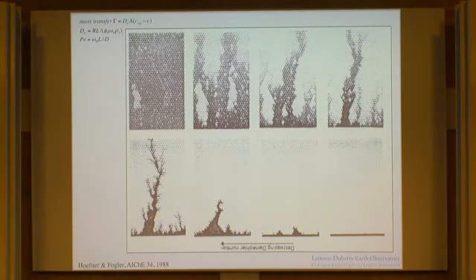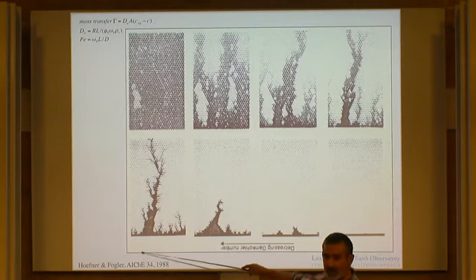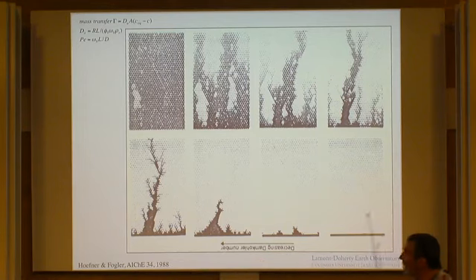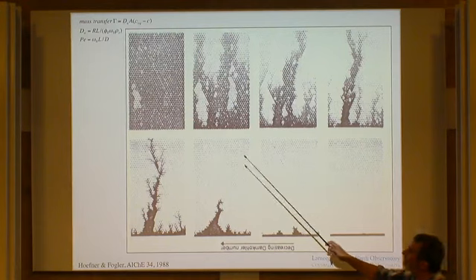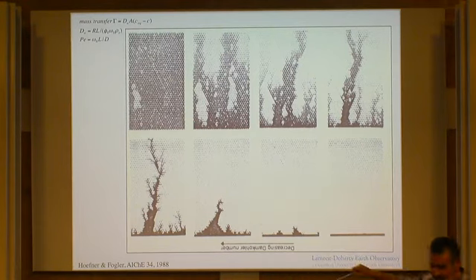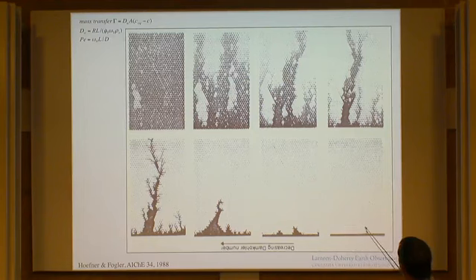I'm going to get through part of this stuff, but that's okay. So there's this nice paper. The oil companies were interested in the dissolution instability, which they called acid flooding, with the idea of using it for enhanced oil recovery. And so there's quite a bit of work done in the late 80s and early 90s, and this is this nice paper by Hoefner and Fogler in American Institute of Chemical Engineering Journal. They did acid flooding of plaster or limestone and got cool looking things that they cast with Wood's metal. I've done this, it's possible for all of us to do this. And then they also had a network model, and I'm just showing you the network model here.